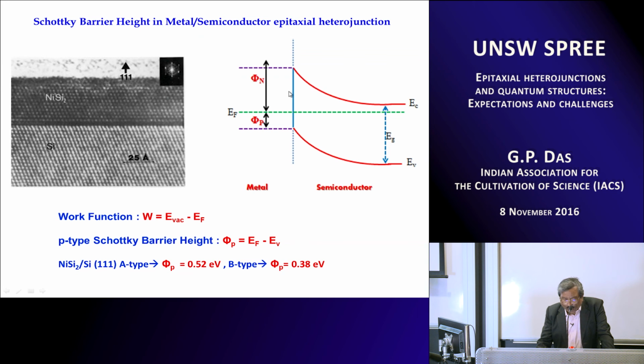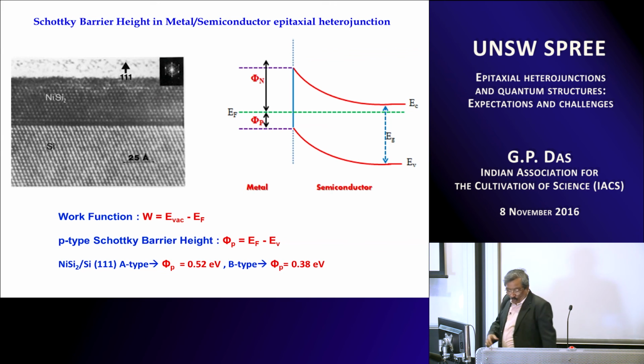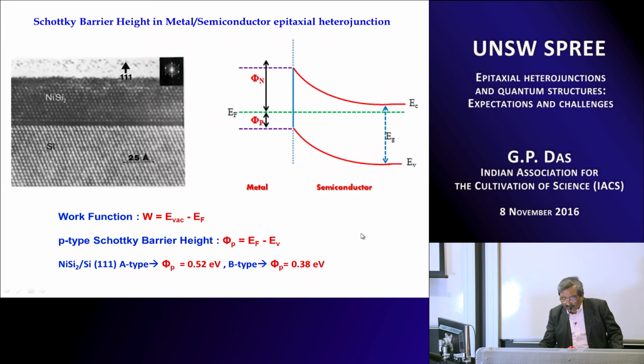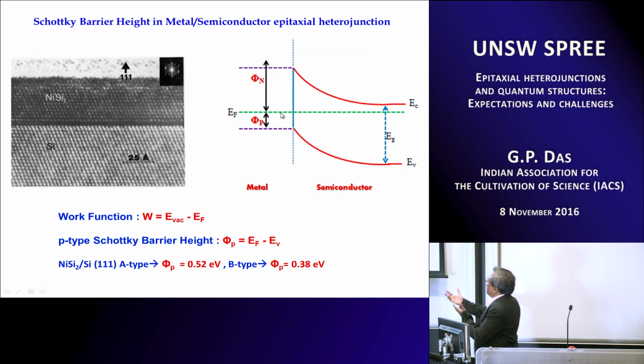So you can find out the work function at the interface from this formula W equal to E_vac minus E_F, and the p-type Schottky barrier height can be obtained by subtracting the EF from EV. So the EF is the Fermi level and the EV is the valence band top. So if you subtract EF and EV, you get what is called the p-type Schottky barrier height. The experimentalists usually quote the n-type Schottky barrier height, which is nothing but EC minus EF, but the two Schottky barrier heights together, the n-type and p-type, is nothing but the gap of the semiconductor.